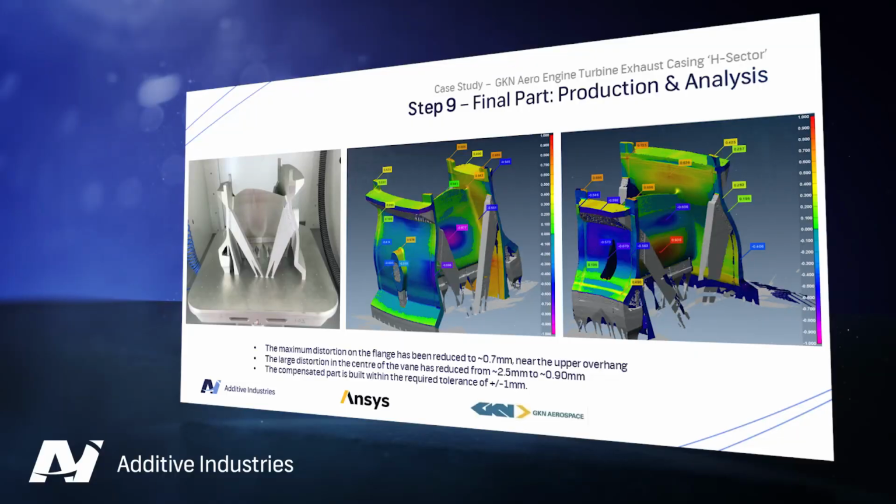The second iteration of the compensated part was 3D scanned, and the surface profile was again compared to the nominal CAD geometry. This time, the data showed that the distortion on the flange had been reduced to 0.7 mm and the vane to 0.9 mm. The part was successfully printed within the required surface profile tolerance.